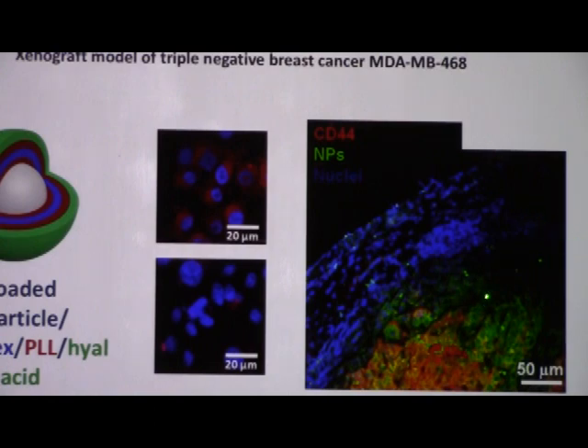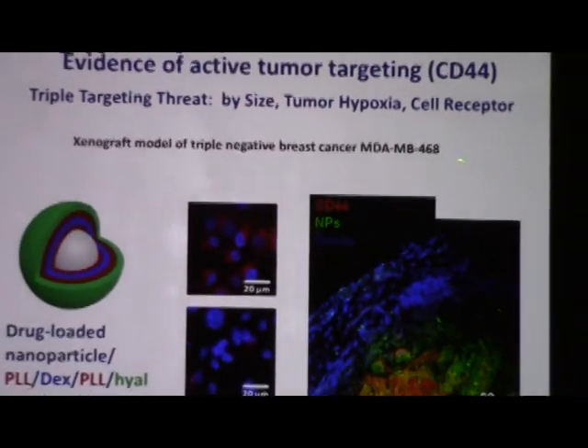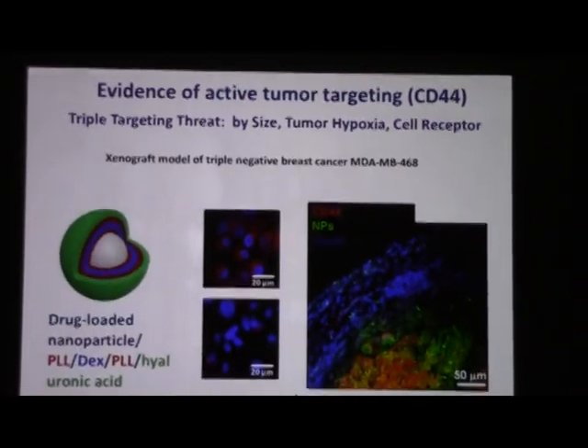On the right, you see a tumor section. And in this section of tumor, again, blue is staining nuclei, and these are cells on the outside of the tumor. They call them stromal cells, but the real tumor cells are inside. And we can stain for CD44, which is that receptor. Here it's shown in red, and you can see the nanoparticles in green, and there's this orangey glow, and that's the overlap of the two. So we're essentially targeting these nanoparticles to tumor tissues using a combination of molecular tagging and changes in the tumor environment. Because we're using size, microenvironment, and the receptor, we call this a triple targeting.